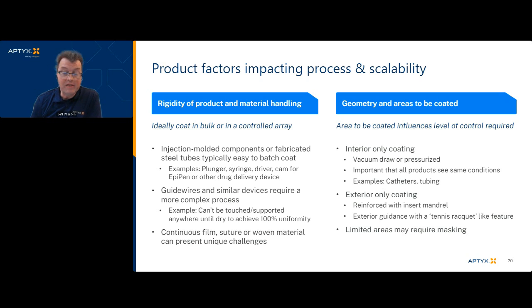Exterior coating only can be done simply by reinforcing some unsupported products interiorly, and that could be a mandrel or a guide rod, or sometimes maybe a fixture similar to a tennis racket. We call them dream catchers as the vernacular around here, that would guide the product with minimal contact area around the circumference of the product and allow that coating to be applied but not detrimentally impact the coating, because we have to guide it or allow it to be nested in a tighter array. That's somewhat important from a standpoint of the volume of the coating. Minimizing the volume of the coating is often key to the success of the project, because in some cases the coatings are very expensive or they have a shelf life. So being able to get the array tighter and being able to minimize that coating solution is also a key factor we evaluate.